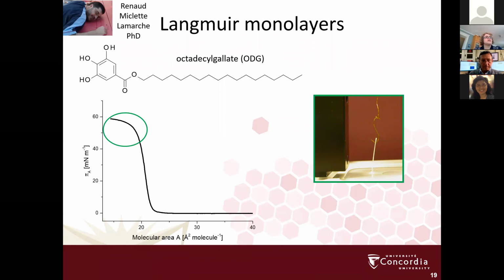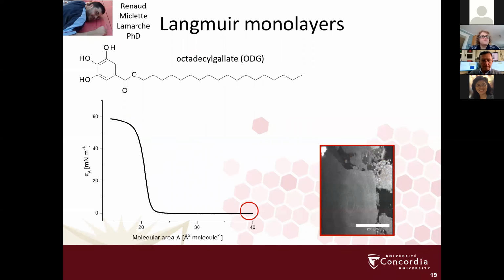And of course, these are just as rigid. You can see, because by the barriers compressing the film, we always get this measurement where we get this pushing of the plate out of the plane. So it's no longer vertical, which means we get this rounding of the isotherm because it's no longer accurately measuring the surface tension. At high molecular areas, yet again, we see that high cohesion that we saw with the previous system, and as we also saw with our double chain lipids.